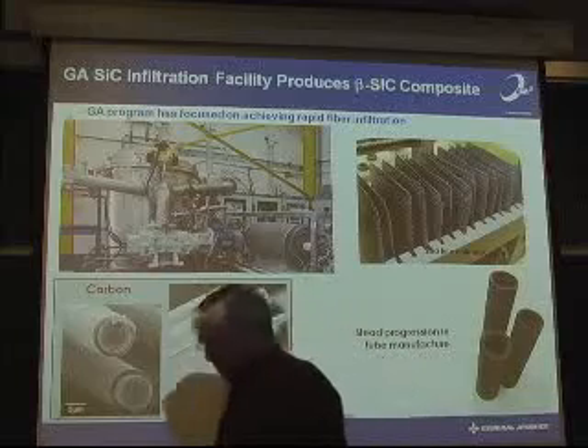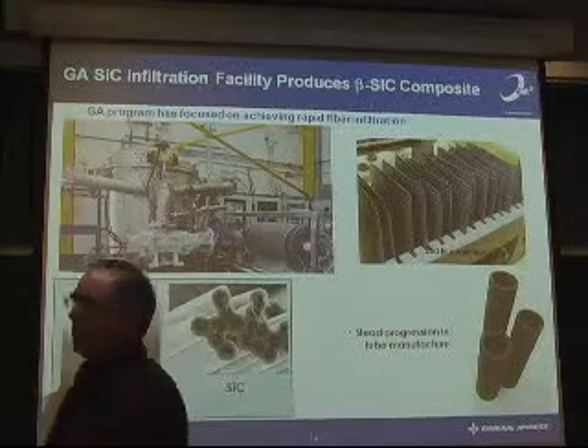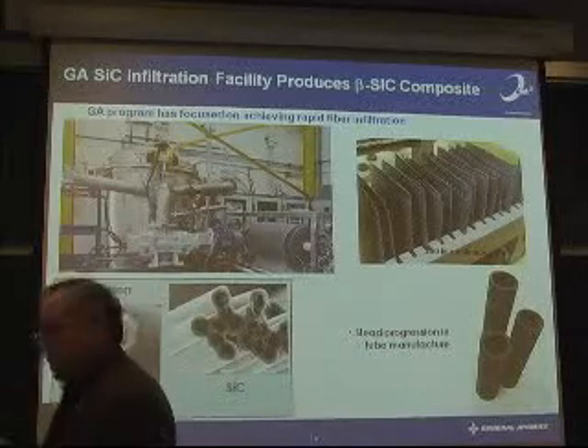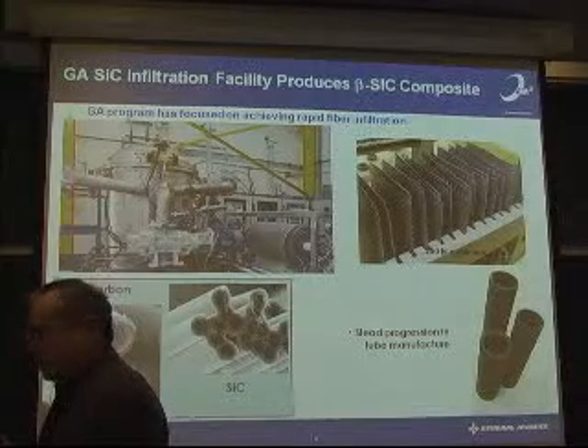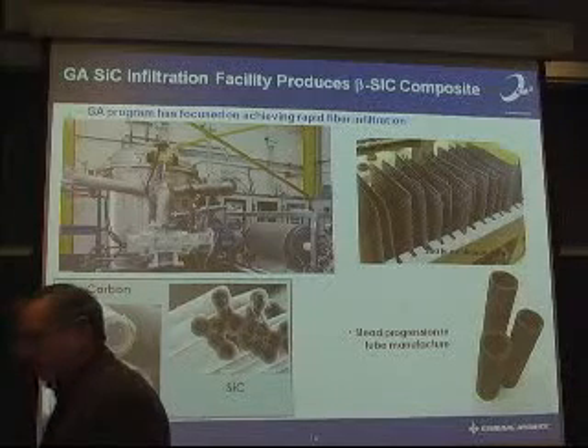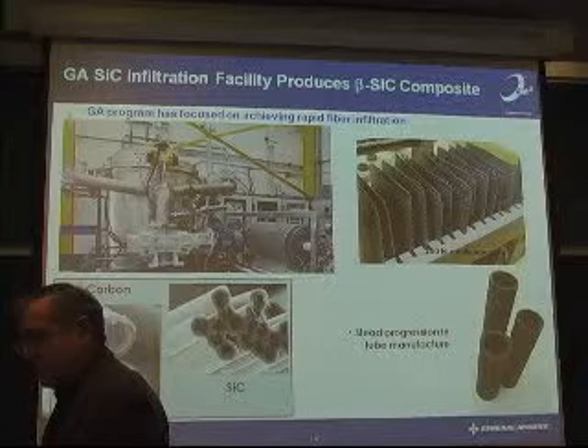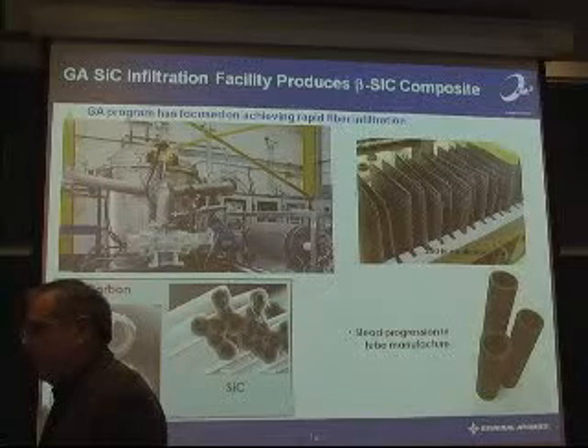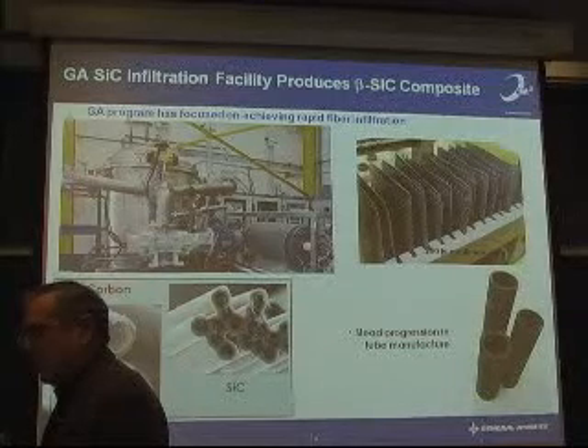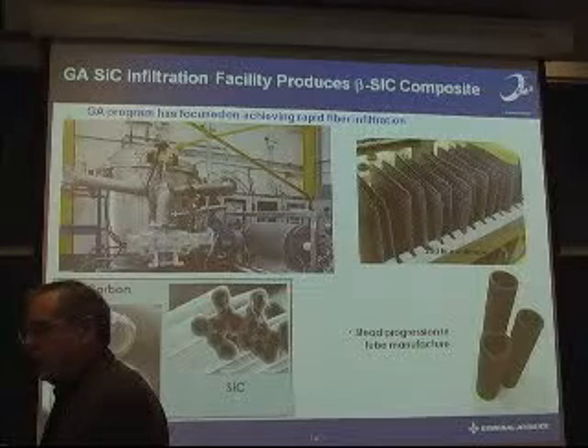That's a good question. No, what do we want in this material? We want a material that has good strength at very high temperatures. The gas temperature is around 850 C at the peak. The peak clad temperature is around 1100 degrees C.